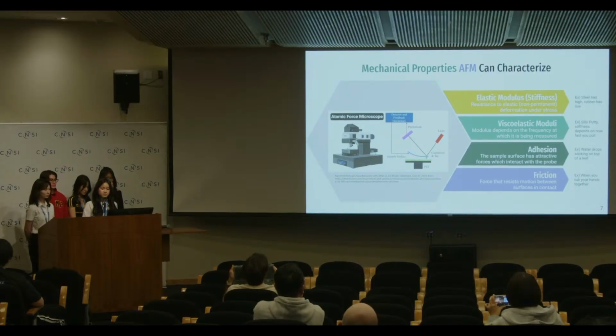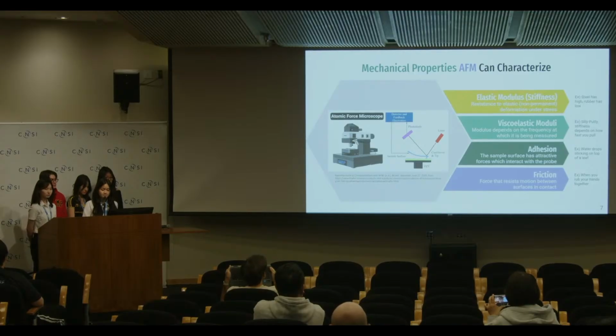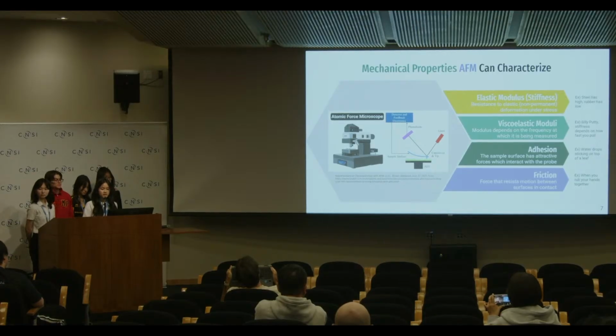Viscoelastic moduli refers to modulus depending on the frequency at which it's being measured. An example of this would be silly putty or oobleck, in which the stiffness depends on how fast you pull it and how hard you hit it. Adhesion refers to the sample surface having an attractive force, which can interact with the probe tip. An example of this would be water droplets sticking on top of a leaf. And finally, friction, which is a force that resists motion between surfaces in contact. An example of this would be when you rub your hands together.